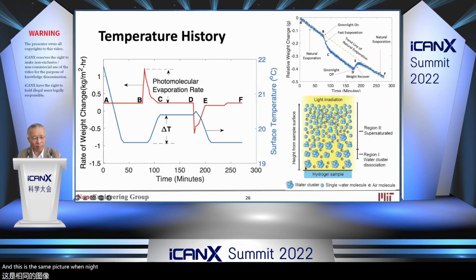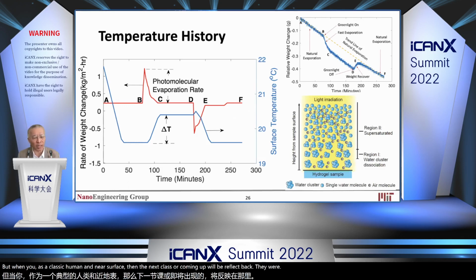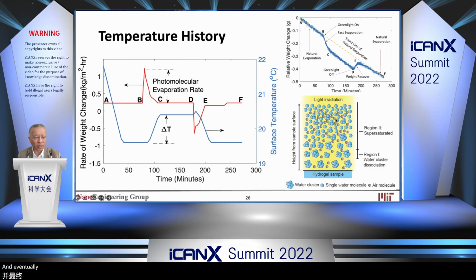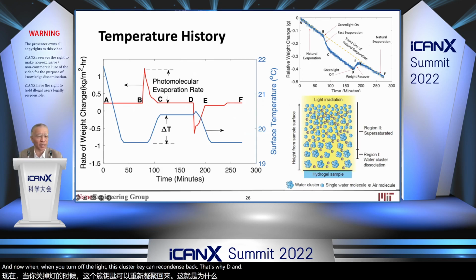When light comes up, it will excite the cluster. But as clusters accumulate near the surface, the next cluster coming up will be reflected back. They will recondense, so they will actually generate heat. That's our picture. Eventually, because the surface is cold, the only way for a molecule to get away is by diffusion, so it really depends on the ambient. That determines why eventually C and D is parallel to A and B. And now when you turn off the light, this cluster can recondense back. That's why between D and E, the weight recovers.